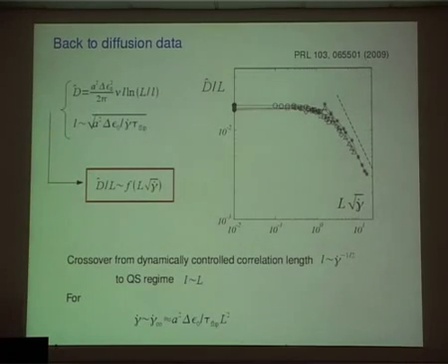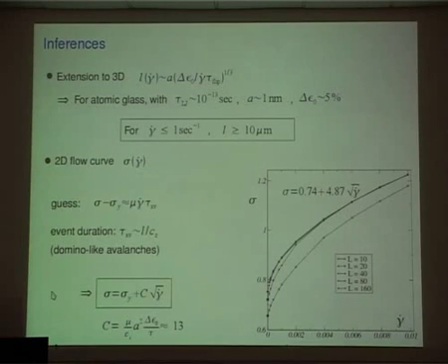So that's the idea we have: this correlation length, when you strain a system, is only set by the fact that you need to distinguish the signals which are coming from the farther away neighbors. That sets a length scale. And beyond this length scale, you just see noise because you are in a large system and you have a huge amount of signals coming in.